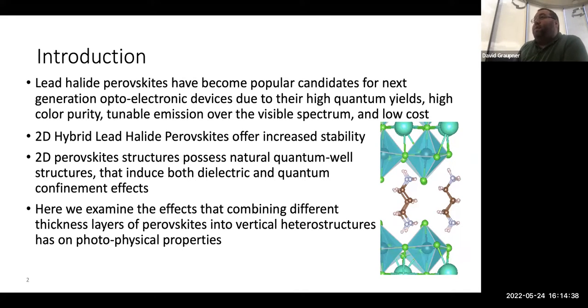The reason I'm focusing on two-dimensional perovskites is their increased stability when compared to the bulk. The 2D perovskites also have a structure that gives us a nice effect where we see a natural quantum well-like structure which induces both dielectric and quantum confinement effects. What I mean by the two-dimensional lead halide is here we have a lead halide and it's separated by an organic ligand and then we have another lead halide here and it just repeats and this forms a thin film.